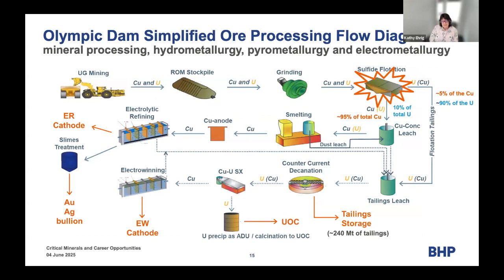So a grossly simplified ore processing flow sheet for Olympic Dam, where we do mineral processing, hydromet, pyromet, and electrometallurgy all at Olympic Dam. Underground mining, and we're just going to really think about the copper and uranium ore stream. Goes on to ROM up on the surface. We have 2 big mills and a smaller mill. Sulfide flotation. During sulfide flotation, where we're separating obviously the sulfides from the gangue, the overwhelming majority of the copper goes into the copper concentrate, and about 90% of our uranium goes into flotation tailings, and that's why we actually leach it to extract that. And it turns out that a fair amount of rare earths are also going out in that tailing stream also.